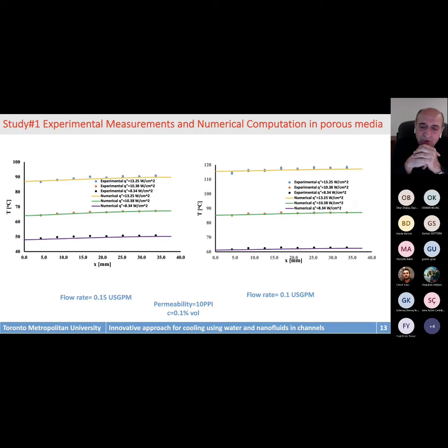But one thing very important to mention here is when you put your porous block on the hot plate, usually we put some thermopaste. And by putting thermopaste, we make sure there is a good contact between the heated block and the porous block. However, when you do numerical modeling, you must model this interface. And by modeling this interface, you can calibrate your thermal resistance for one case and use it for the entire correlation between experimental and numerical.